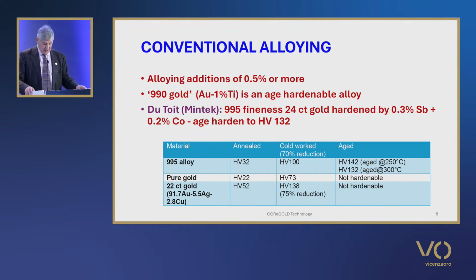If we look at conventional alloying, here we're talking of adding alloying metals in amounts of at least 0.5% or more. The addition of 1% titanium to pure gold to produce 990 gold has been referred to previously. Other significant improvements to 24 and 22 karat golds have been described using conventional alloying approaches.